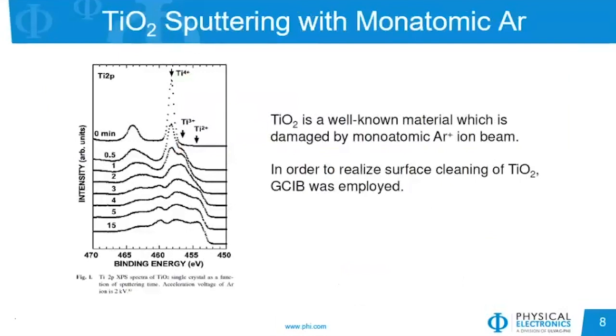So to start with, I have an example showing what happens if we try to clean and actually profile through titanium dioxide with monoatomic argon. This is well known to cause damage and reduction of the titanium as shown by the Ti2P peak. As we start at the top at 0 minutes, we see a sharp peak of the Ti4+ state, but as we continue to sputter with monoatomic argon, there is a peak that develops to the lower binding energy side, which represents damaged and reduced states. So if we wanted to clean TiO2, it may be difficult with monoatomic argon.